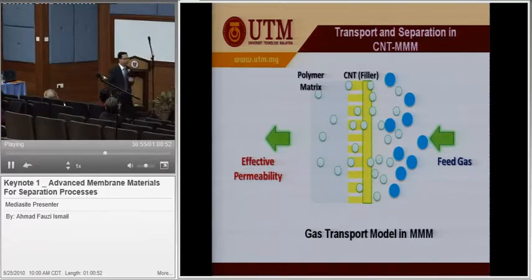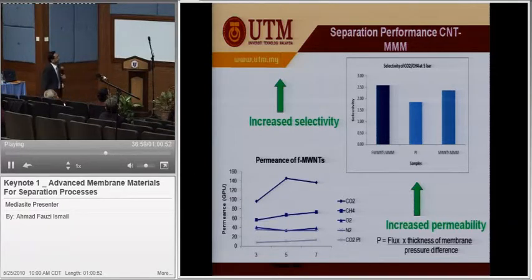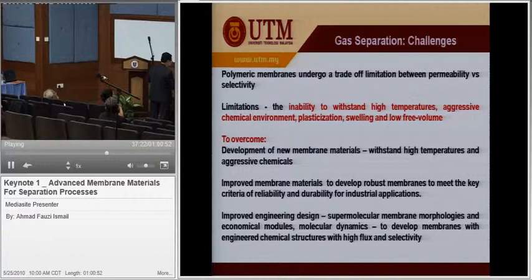Now, some of the performance data that we got from the lab, you can see here. Never mind. The upper one is for CO2, and this one for methane, and this one the data without CNT. Huge improvement. So you can see clearly here, this is the selectivity of the functionalized multi-wall carbon nanotube mixed matrix membrane compared to the rest. You can see the huge improvement in terms of membrane performance.